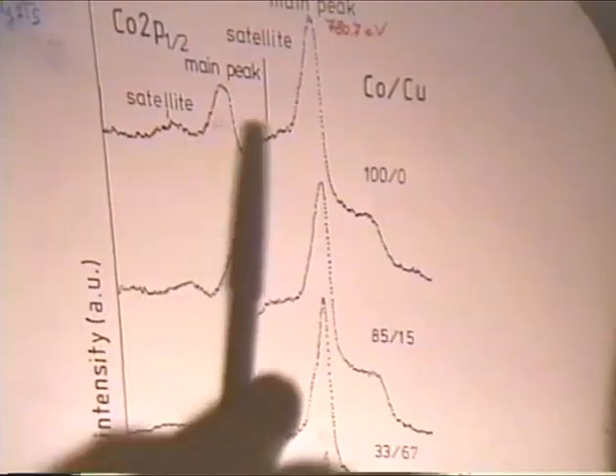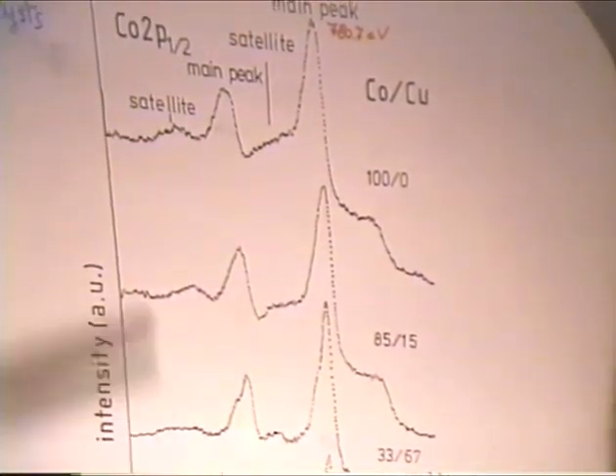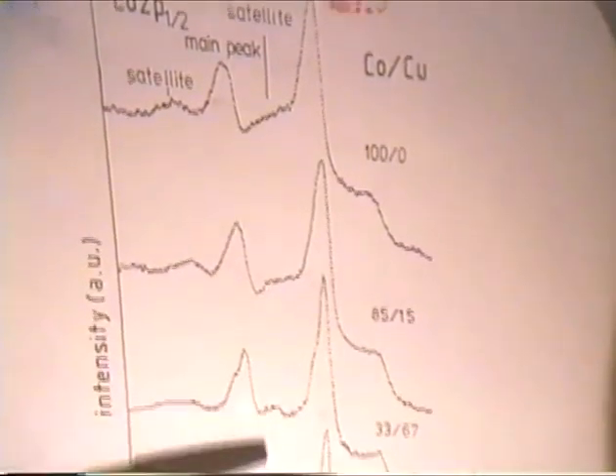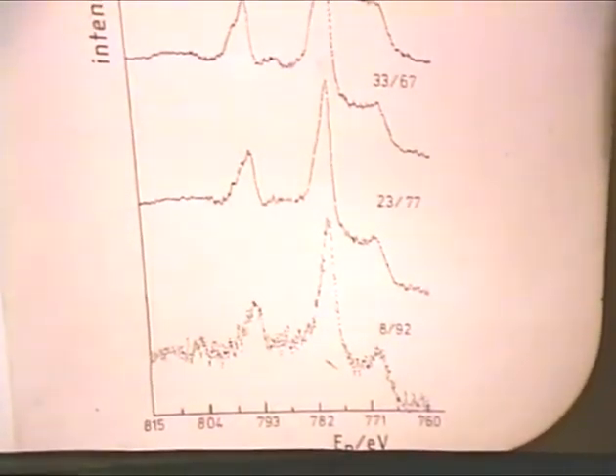So when copper is added to the catalyst, what is observed is a decrease of the intensity of the satellite peak and a slight shift of the binding energy of the main peak. So both these features suggest that a reduction of Co3O4 species occurred. In fact, it's well known in the literature, and this is an anomaly in the XPS, that there is an inverse shift of the cobalt 2+ and the cobalt 3+ binding energy. Namely, the binding energy of cobalt 2+ is higher than the binding energy of cobalt 3+. And moreover, in cobalt 2+ containing compounds, the satellite peak is virtually absent.